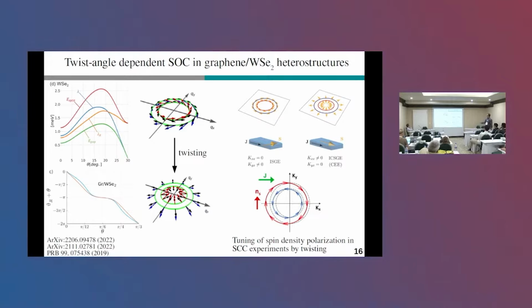But if you then switch into this radial spin-orbit field, you can also tune the polarization of your spin density. So it can become collinear to the applied current. So with the twist angle, we have actually a knob to tune the polarization of the spin density.